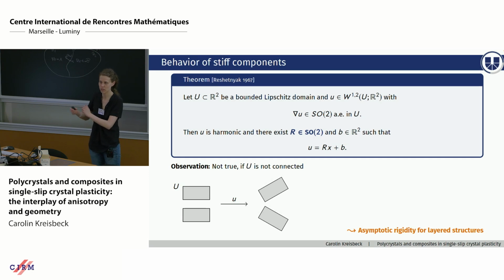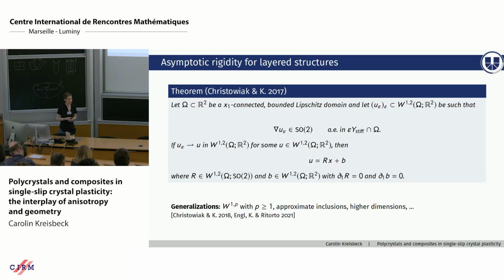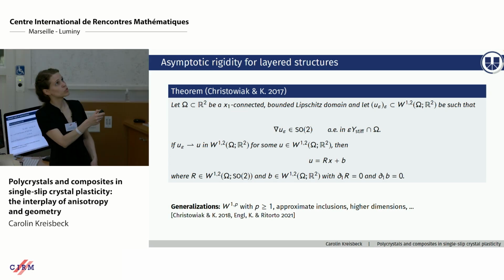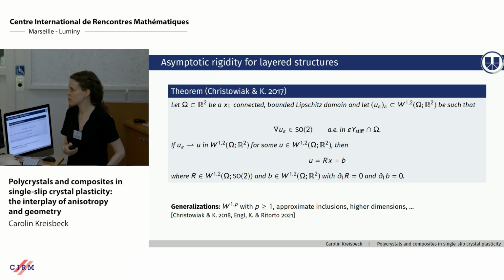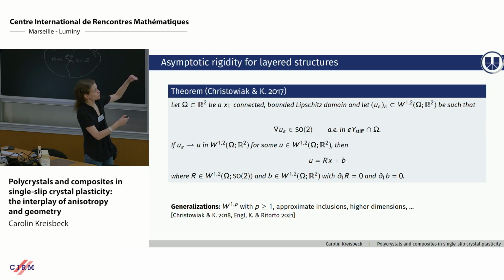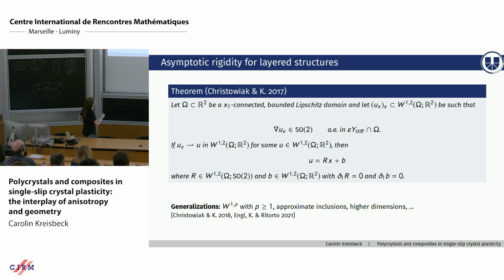So this is like an asymptotic result. And that's why we speak here of asymptotic rigidity for layered structures. And so the theorem reads as follows. So if we have a sequence of W^{1,2} functions that converge weakly to some limit u and whose gradients lie almost everywhere in SO2 on the stiff components, so just there, then we know that our limit deformation here has the form Rx plus b. So now it looks almost like it did before, but now watch out. Here R is a Sobolev map, and so is b, but it's independent of the x1 direction, so the layer direction.